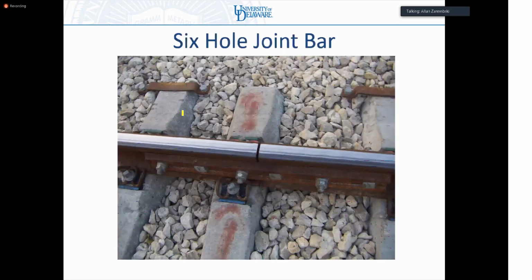So this is a 6-hole joint bar. Usually we use 6-hole joint bars for the larger rail sections. For a smaller rail section, you can get away with a 4-hole joint bar. Notice there is one bar on each side. It fits into the web of the rail between the head and the base, and then it's bolted through the web. So you have to drill holes through the web and insert these bolts and tighten them with the nuts. You notice the bolts are in alternate directions, left, right. That's in case there's a derailment. So if a wheel came along and sheared off the nuts, the bolts will still be in place and would prevent the rails from coming apart.